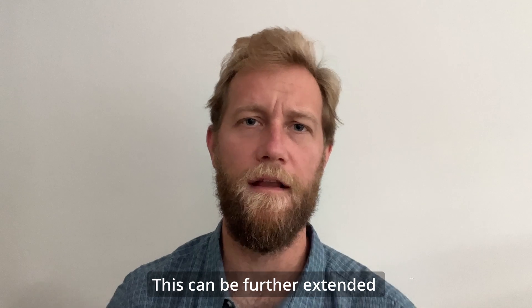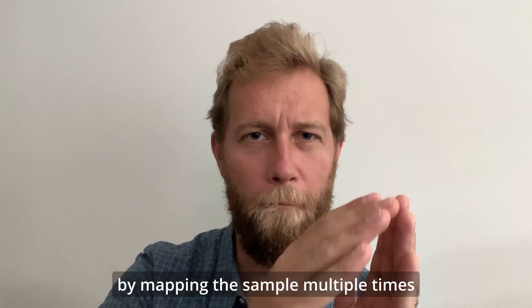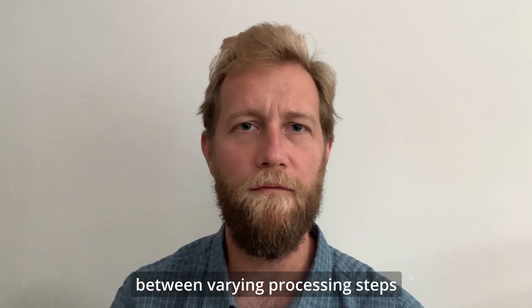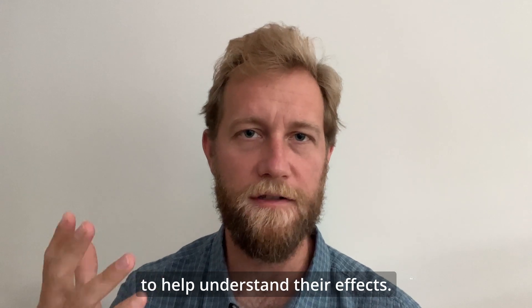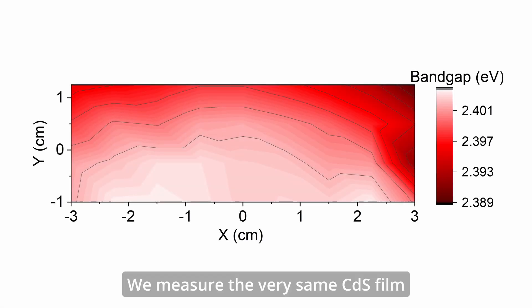This can be further extended by mapping the sample multiple times between varying processing steps to help understand their effects. So here, we measure the very same cadmium sulfide film after it has had a heat treatment anneal to investigate any changes.